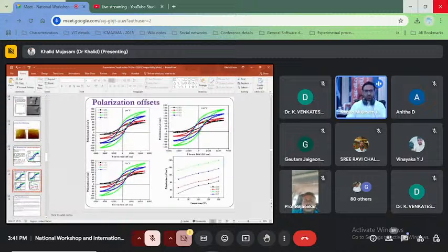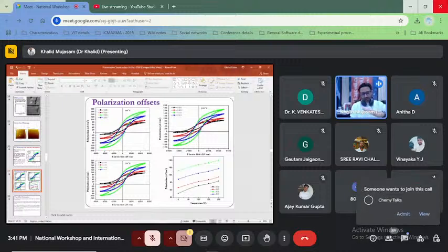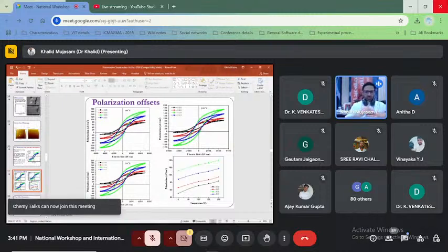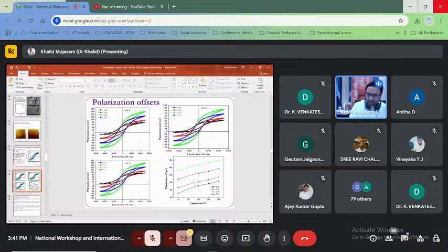However, we did one more thing, which has not yet been communicated. This part is still under investigation. What we did was that the bottom of the film was being heated while we were not heating the top one, and we used the top electrodes and this P measurement. What we saw after heating is an opposite polarization.